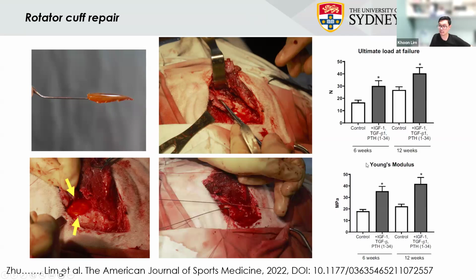And what we did see is at both 6 weeks and 12 weeks, with the hydrogel and the specific growth factor cocktail that we have put in at this time, you see an increase in the biomechanics. So these hydrogels are there, and at both time points, they did facilitate tissue regeneration of the rotator cuff to increase the biomechanics. So they are functional as they are being released from the hydrogels.